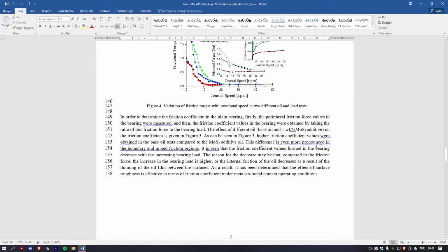It's seen that the friction coefficient values formed in the bearing decrease with the increasing bearing load. The reason for the decrease may be that, compared to the friction force, the increase in the bearing load is higher, or the internal friction of the oil decreases as a result of the thinning of the oil film between the surfaces. As a result, it has been determined that the effect of surface roughness is effective in terms of friction coefficients under metal-to-metal contact operating conditions.